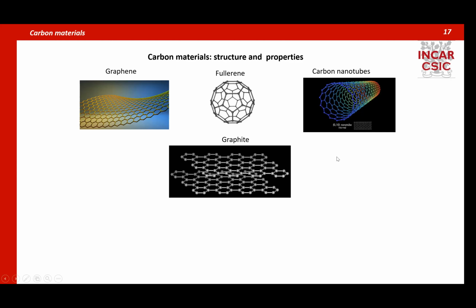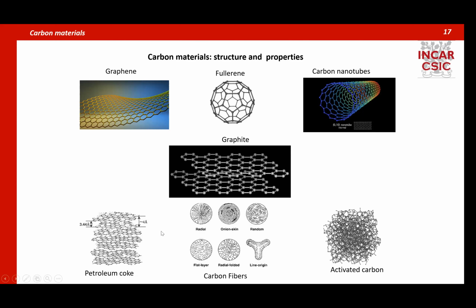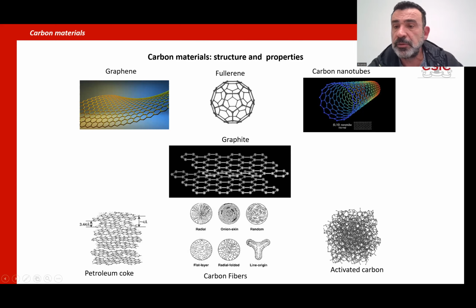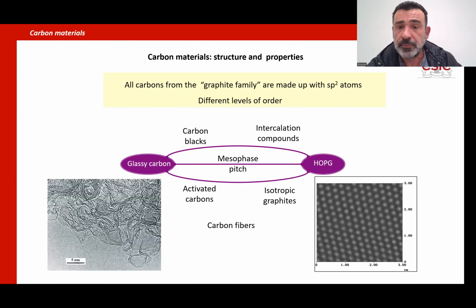Then all these materials are related with graphene, with graphite, and there are more traditional materials like petroleum coke, carbon fibers, activated carbon that has been used for more than a century in many applications, as I showed you before. The reason depends on the different levels of order of the carbon atoms. And we saw that in graphite and diamond, everything is related with the position of the atoms. Again, within the family of the graphite, everything depends on how they are disposed in the space.